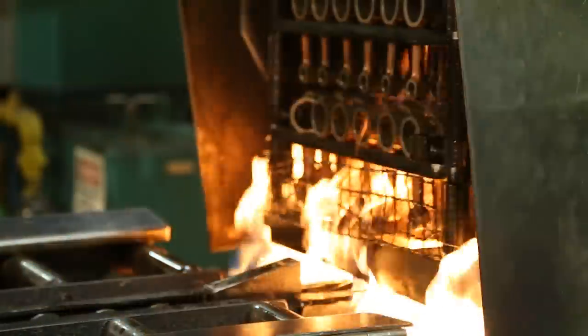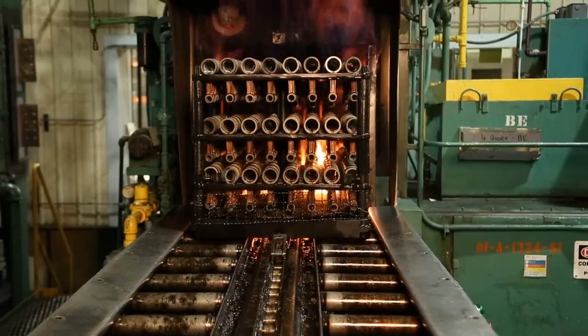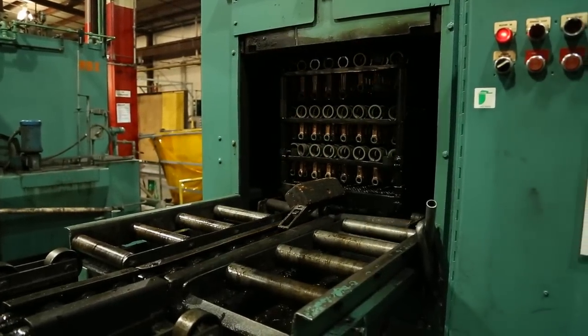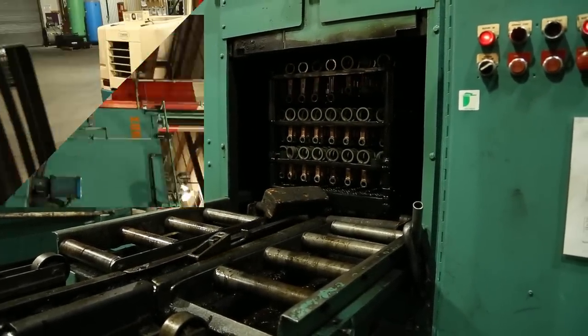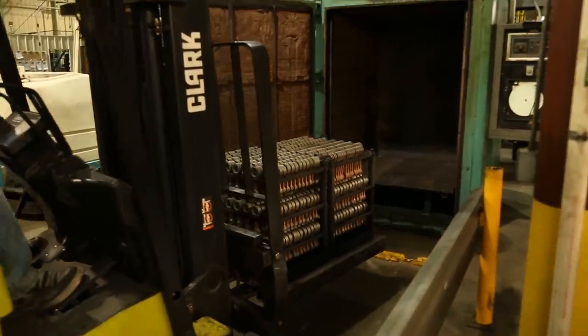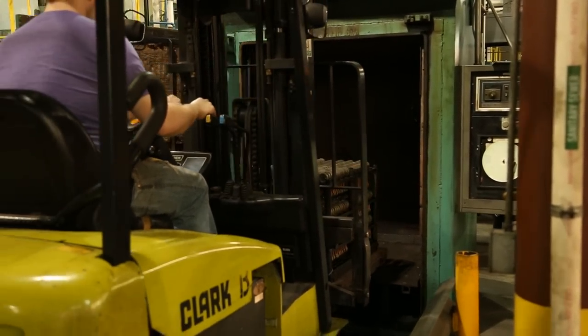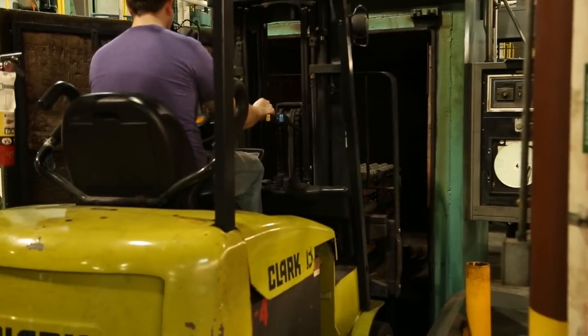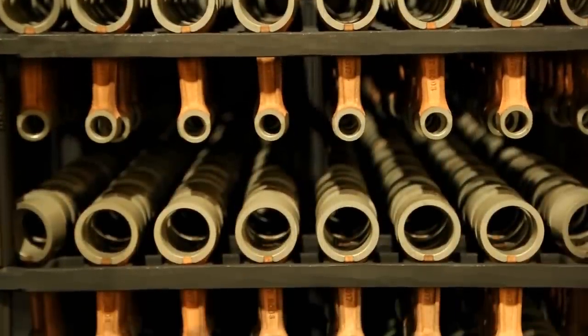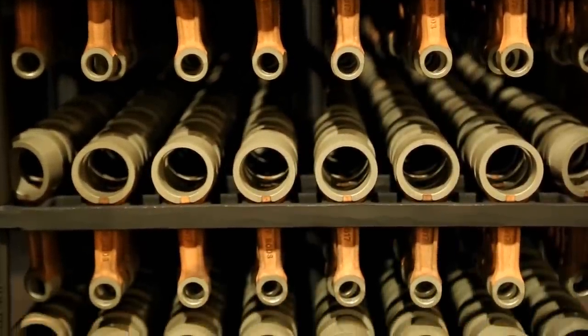After 10 hours inside the furnace, the rods are quenched in oil and come out to go through a hot water bath. After the oil is rinsed, the rods are then placed in a tempering oven and brought back up to 350 degrees. This specialized process is critical in ensuring the hardness of the bearing surfaces of each rod before they get finished, ground, and honed.